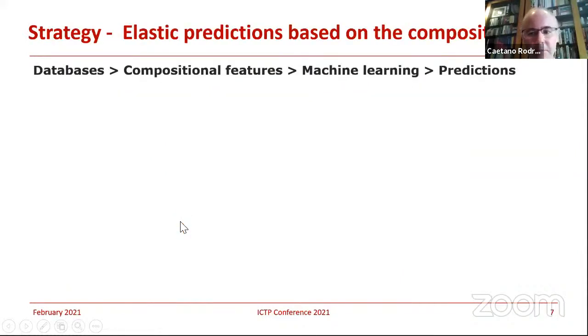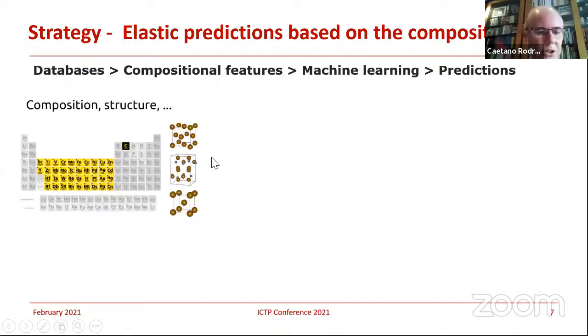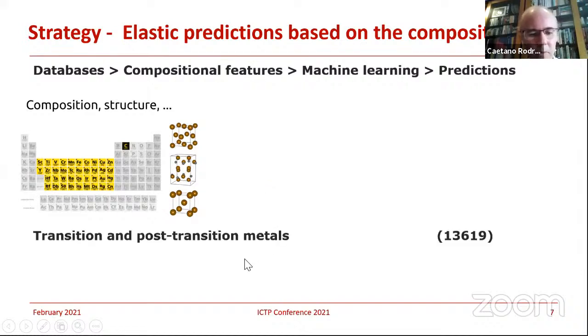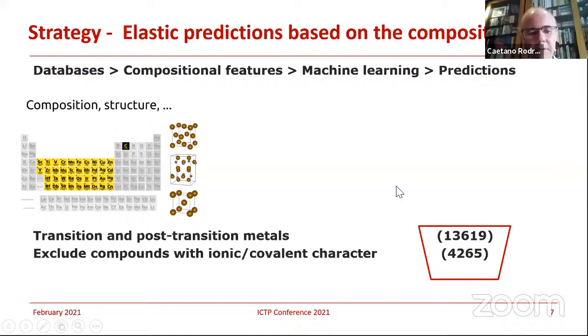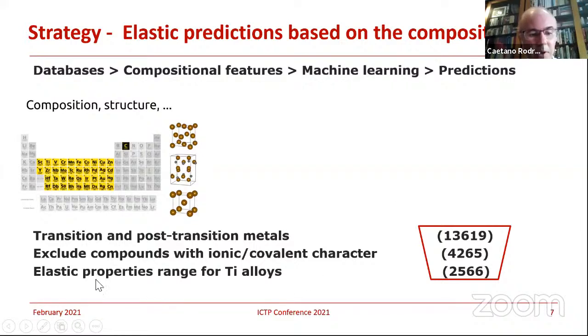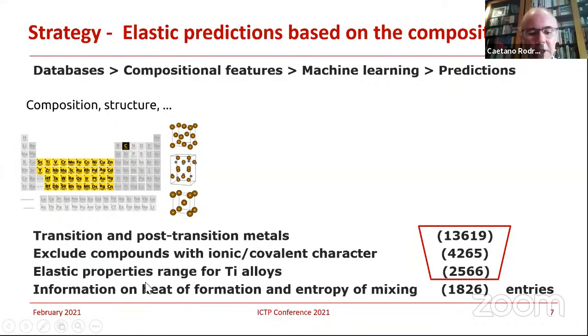Now, how have these several steps been done on the way to reach the full alloy and the material itself? So we start with the composition structure, as has been seen in several of the talks today. You narrow down the possibilities, looking only for the transition and post-transition metals. This gives you this amount of entries. Now you filter out even more. You exclude any ionic or covalent character of those systems. Then you look also for elastic properties in the range of titanium alloys, that is interesting for us. And finally, the information that comes from the heat of formation and the mixing entropy. So this gives us around 2,000 entries.